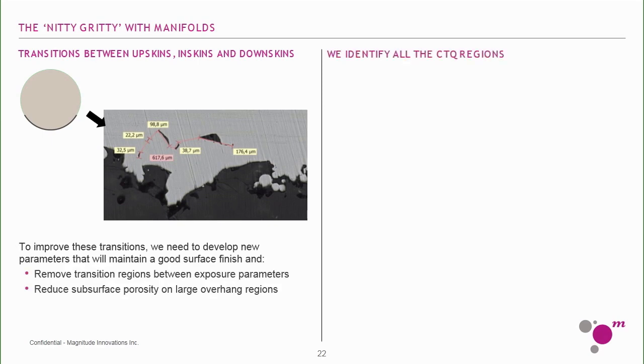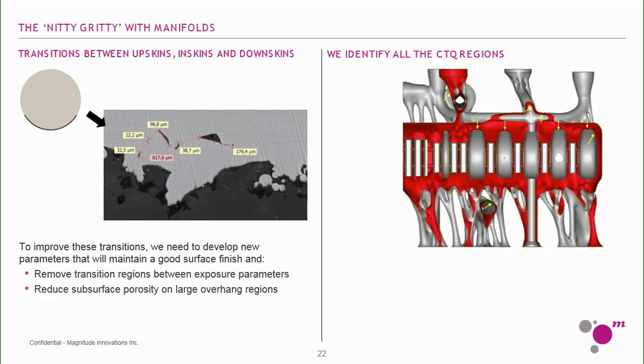And at the same time, we focused on making sure that the roughness in the geometries on the downwards facing areas and upwards facing areas is more homogeneous, because when it's homogeneous, the post-processing costs go down. So we defined these critical to quality regions. And we went through, I think, like 10 different iterations with the designers in order to improve the internal channels, to minimize those angles, to make the area self-supporting. So even though you can see a horizontal structure here, orthogonally speaking, when you take a look at it from a 90-degree perspective, it's self-supporting. And where it wasn't self-supporting, we had to keep in mind that we have to make it machinable.